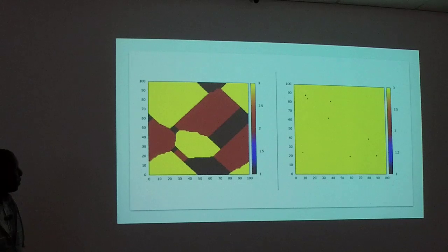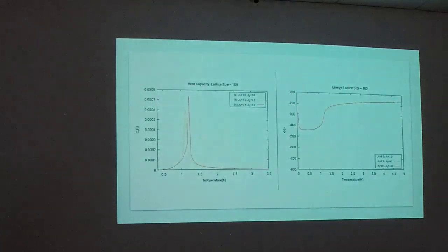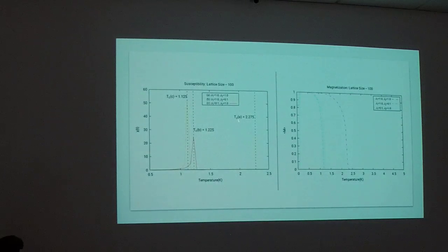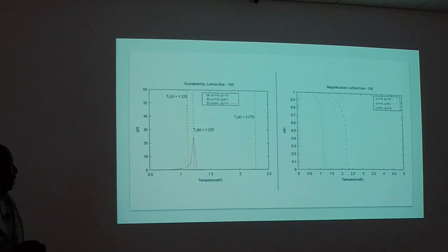homogeneous arrangement to a more randomized one, right? And again, this is the susceptibility, the variance in the magnetization in this case. And you can also see how, when you change your parameters, it affects how the transition happens, right? So if I have very large parameters, you see it's second order, and as you reduce your parameters, it comes to almost a first order transition, right? And again, you can check exactly where that transition happens by looking at the peak in these susceptibilities.